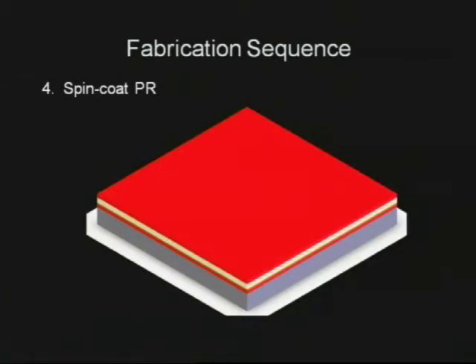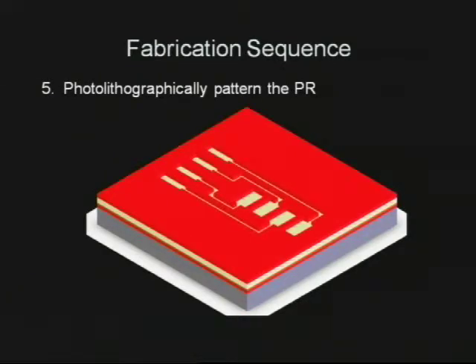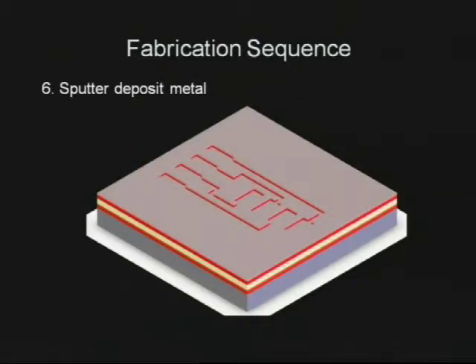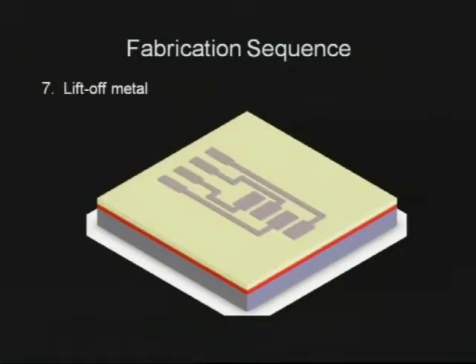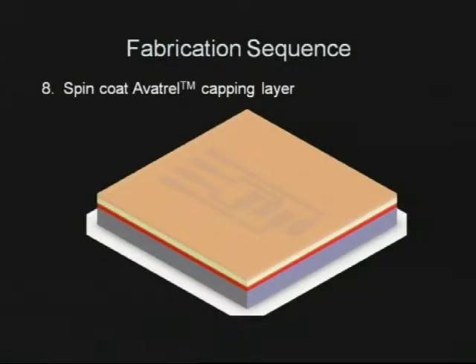We then would spin coat some photoresist, and pattern the photoresist using conventional lithographic patterning techniques into structures that would resemble electrodes. We would deposit the electrode material right onto the substrate. In our case, platinum is the principal material. Sometimes we use gold, and we're looking to use other ones like indium oxide and the like. We would then perform a simple liftoff of the unwanted platinum that sits on top of the patterned photoresist, leaving behind patterned metal that sits directly atop the liquid crystal polymer. We need a capping layer to electrically isolate the interconnect traces from the environment.